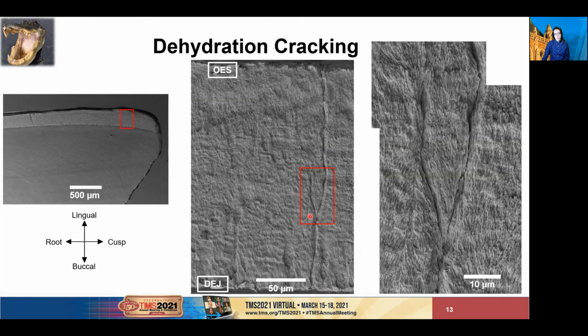Looking a little closer, we can see the direction that the crack bifurcated here confirms that the crack had to originate at the DEJ and move towards the OES. You can also see towards the bottom of this center micrograph the gaps between columns which are serving as seed cracks that are then propagated during dehydration.